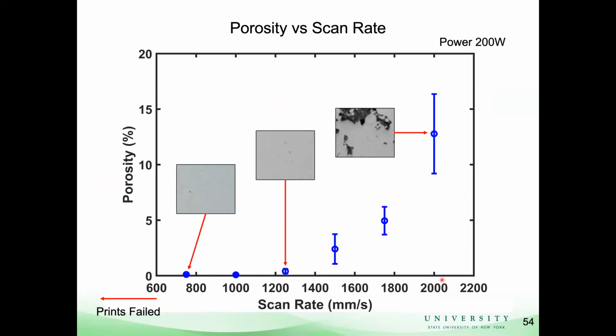So here's a plot of porosity versus laser scan rate. At faster scan rates, we start to have high porosity. This is too fast a scan rate, and what we get is incomplete melting. You can see here that there are some regions that are not fully fused together. When we slow down the laser, we start to get less porosity, and there's a plateau here around 750 to 1000. This is the machine spec process parameters for stainless steel.